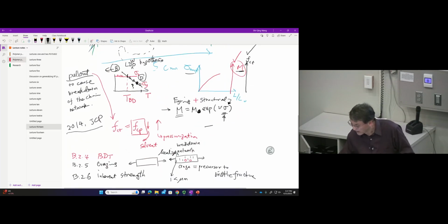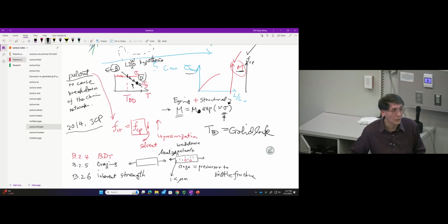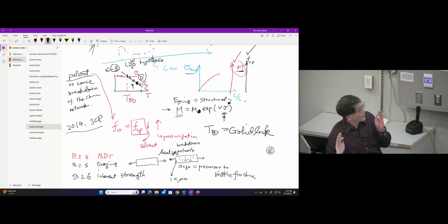And of course, this point is what I call the Goldilocks temperature. If I teach this in Europe, I cannot use Goldilocks because they don't know what it means. I checked with them. Goldilocks is our three-bears story that we give to our kids. So it's a just-right temperature. If it's hotter than this temperature, you have no trouble activating and getting yield. If it's too cold, you cannot do anything. It breaks apart. So that temperature is the temperature at which the network was marginally able to complete the job, and is also the point where the network is about to fall apart as well.